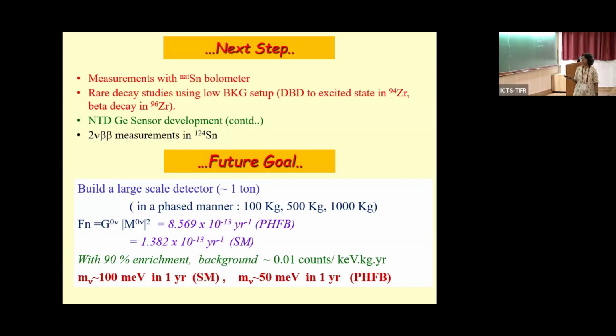The projection for the tin detector, again, if you do it like all others, we have to go in a phased manner, but if you had a 1-ton detector with about 90% enrichment, achieving the background of, this is a very crude estimate of background. We hope with all the techniques you'll be able to do better than this. You can get a sensitivity at this level.